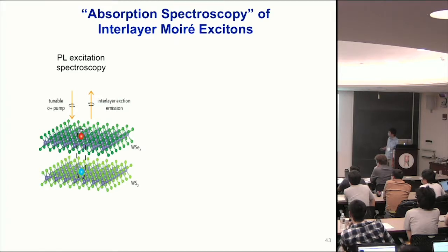So that actually provides a very sensitive detection of the optical absorption. And the main advantage of this one compared with a direct absorption measurement is that it is background free. Because if you just do a regular photon absorption, the difficulty is not detecting your signal, it's more that the background is too large. You have a transmitted light, and your signal is really overwhelmed. On the other hand, in this case, if you don't have absorption, you don't have any photoluminescence. So you measure only the net absorption.